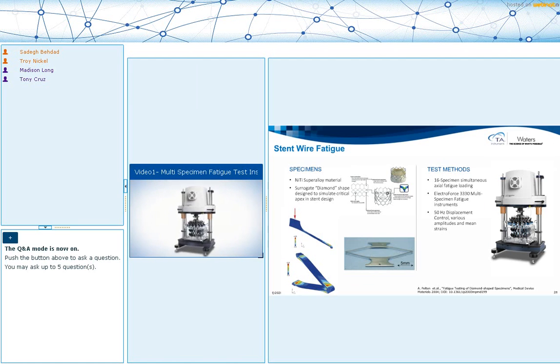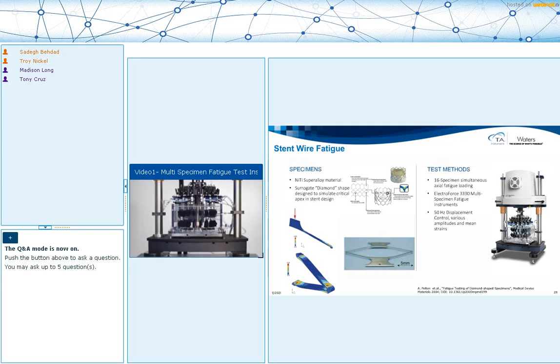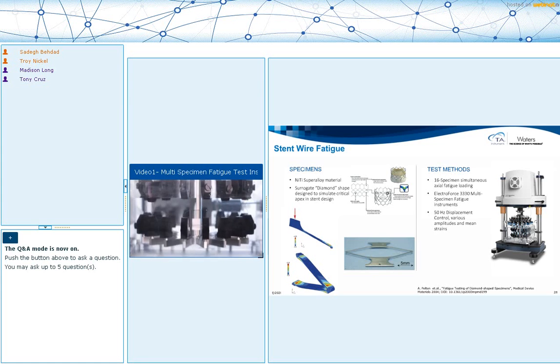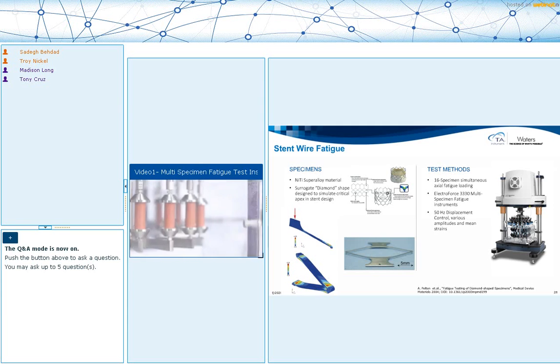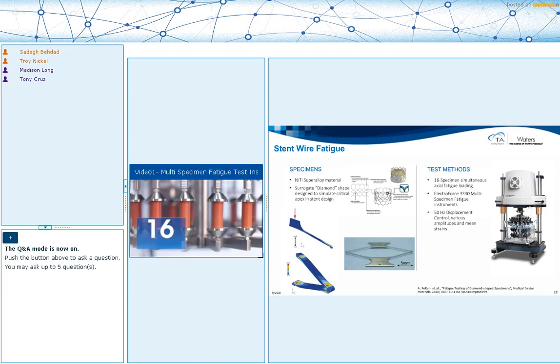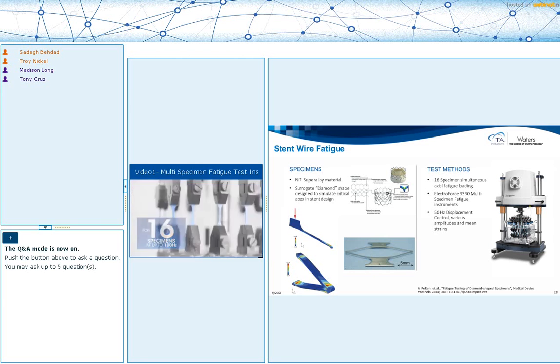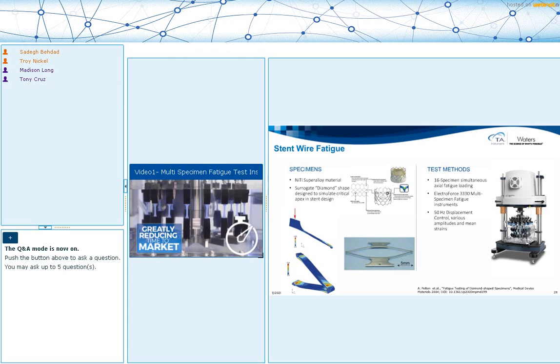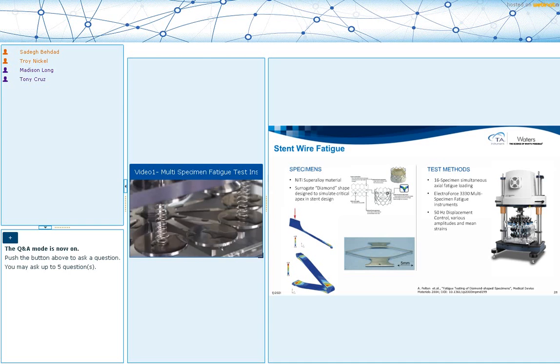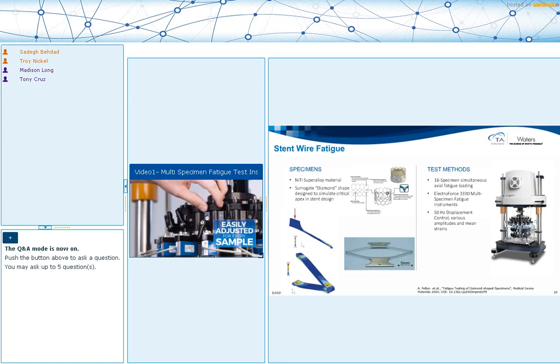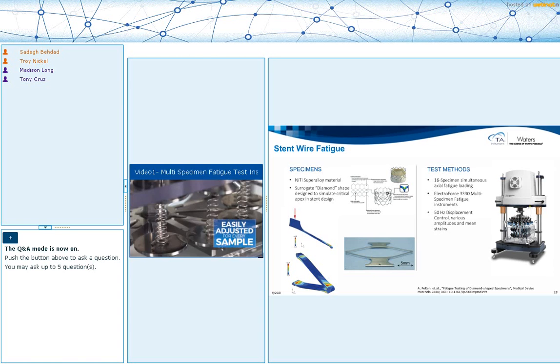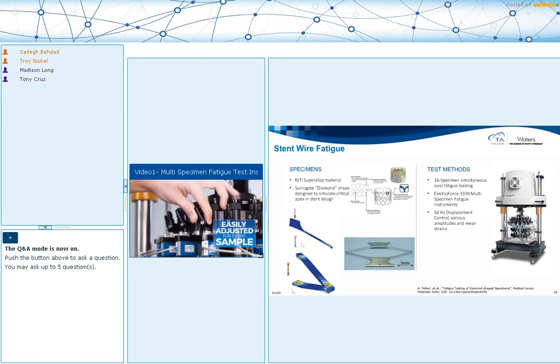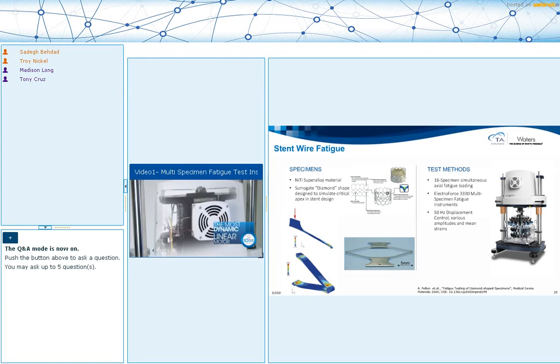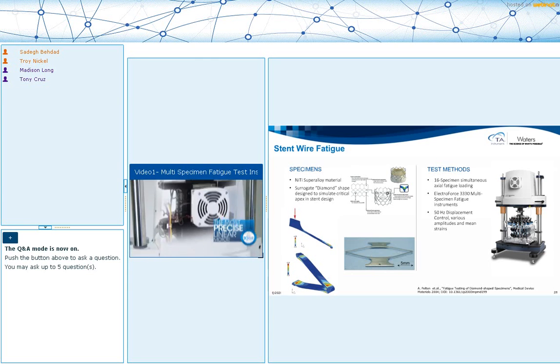So what we are doing here is we are using a star-shaped accessory, attached to our load frame to translate that deformation to 16 stations inside a bath at the same time. And you can test your samples either in compression or in tension. And on each of those stations, you have a load cell. So when your sample breaks, you can measure that load drop and know how many cycles it took to fail that sample. And because you have 16 data points, you can establish the statistically valid bounds that we talked about earlier, and I'm going to show in the next slide, to create a design curve.